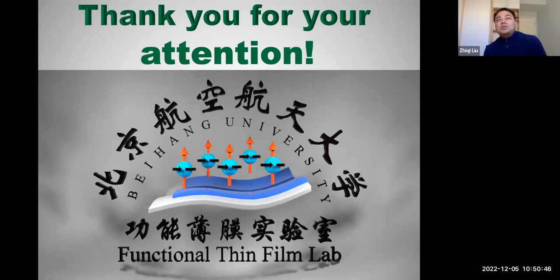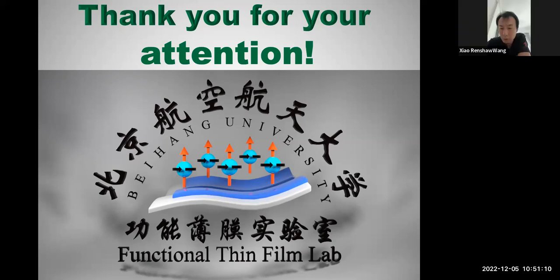So I don't think you could really avoid this kind of surface roughness because they are ferroelectrics. They have different ferroelectric domains. The roughness you see via the atomic force microscope could be intrinsically due to the domain boundaries of ferroelectric domains. Okay, great. Thank you very much. So basically, your material is perfect for PMN-PT. You don't have this problem, and the PLD could be difficult.